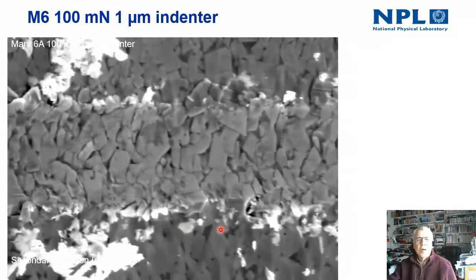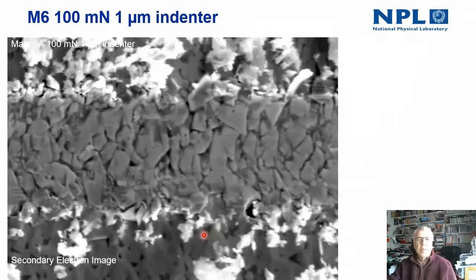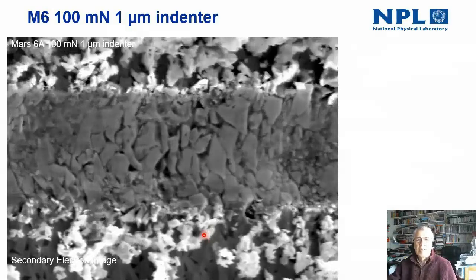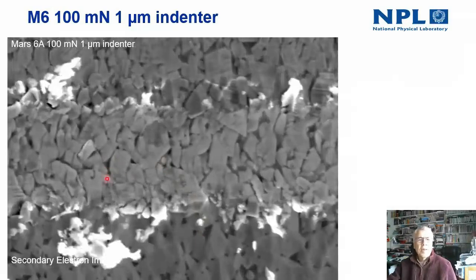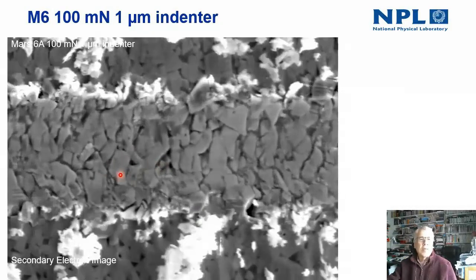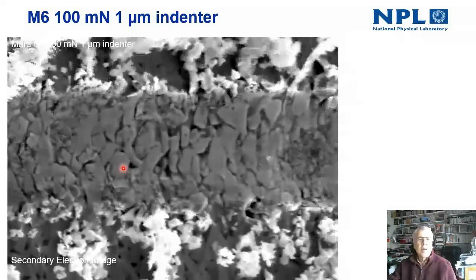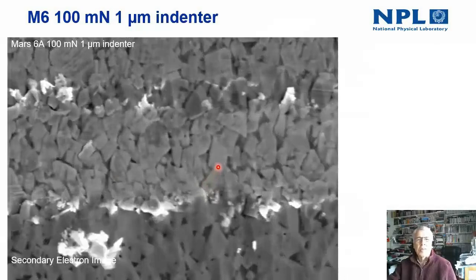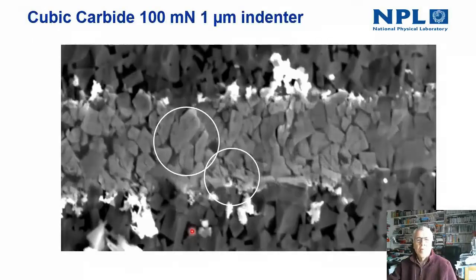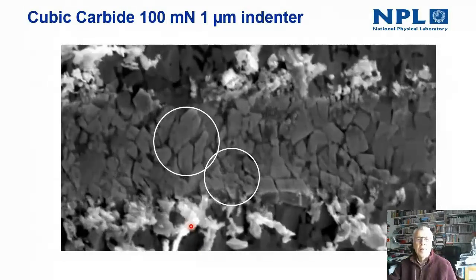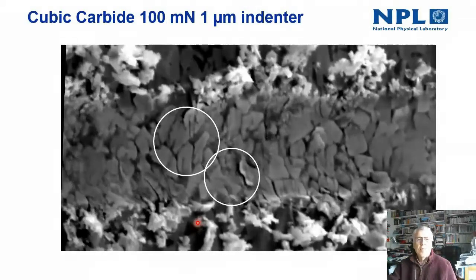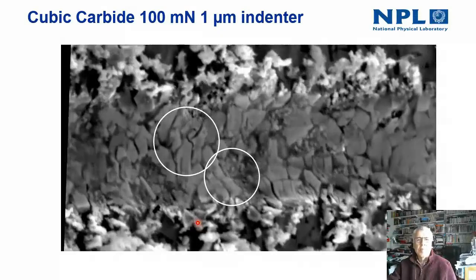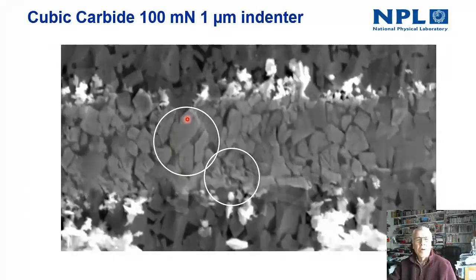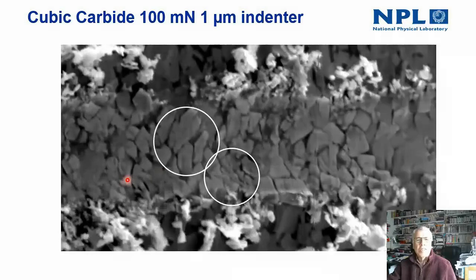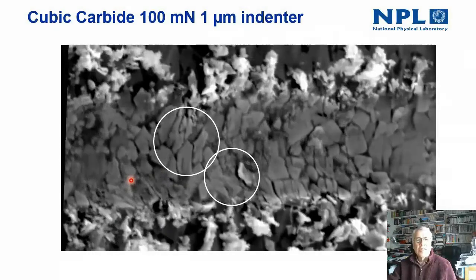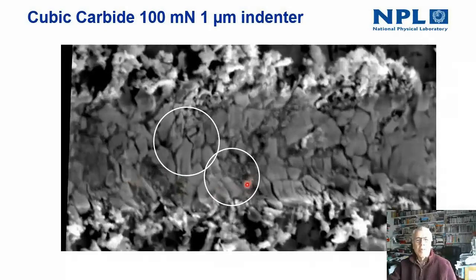This shows another tungsten carbide cobalt material, in this case a finer grain size material, and you get somewhat different behavior from this. In the early stages of the experiment you can see quite a lot of slip line traces in the grains, but again you're getting fragmentation and fracture. And then finally, here's a cubic carbide containing tungsten carbide cobalt material, and if you look at the circles in particular, here are areas where there were specific grains which eventually accumulate damage and then just break apart and fragment and are removed from the surface.